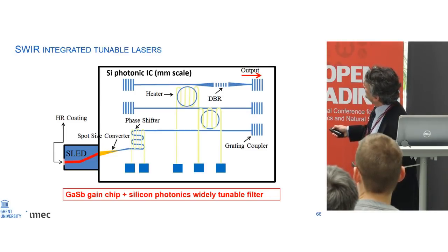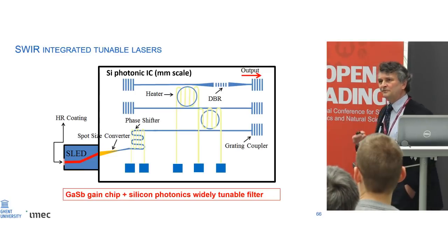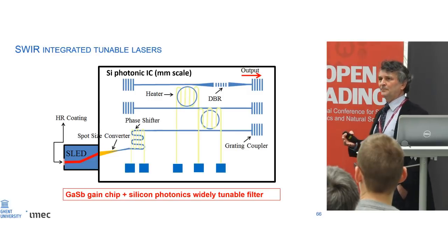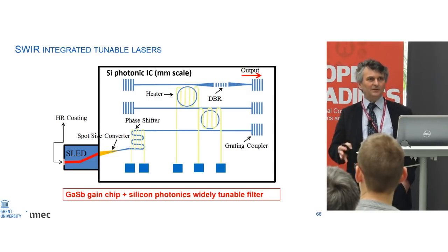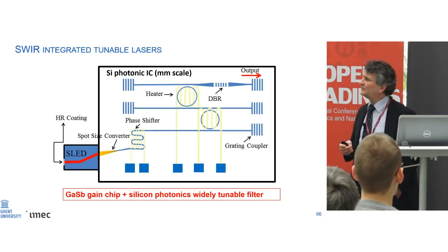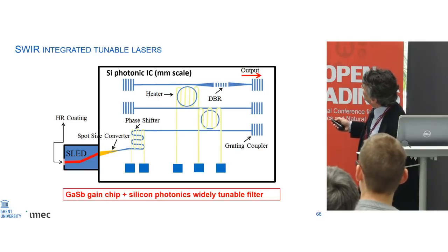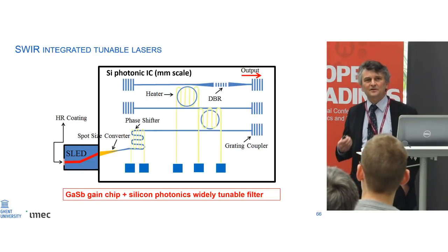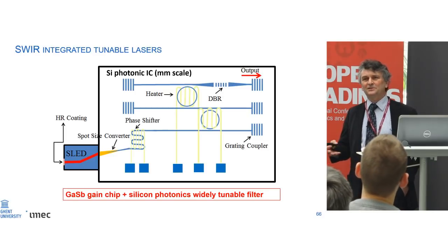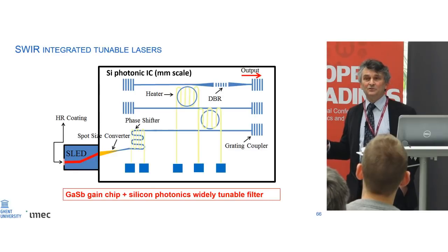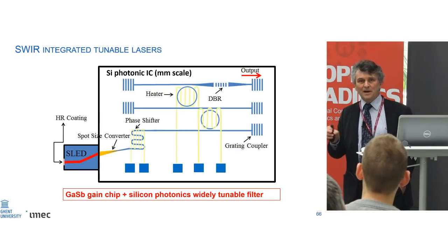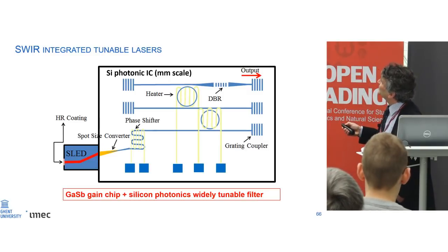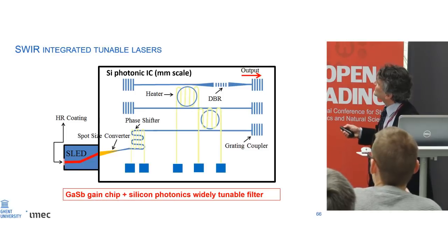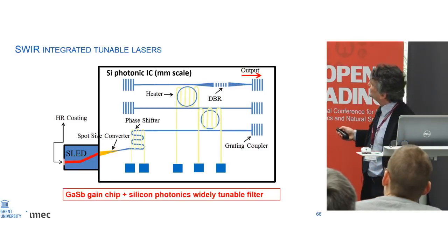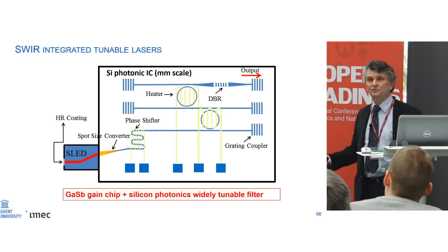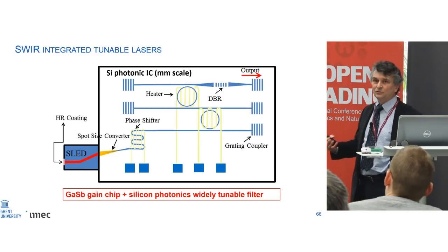And then on the silicon chip we have a variety of structures, and these are optical filtering structures, and basically they provide optical feedback to the gain chip at well-defined wavelengths. And actually in this case, I've added, and these are these lines here, micro heaters. Because if you change the temperature of silicon, its refractive index changes, as you can imagine. So that means that you can shift an optical filter by simply micro-heating locally on the silicon chip the devices that provide the wavelength selectivity. In this case, there are these ring resonators. So by playing around with the currents through these micro-heaters, I can change the optical filter, and thereby I can eventually make a tunable laser.